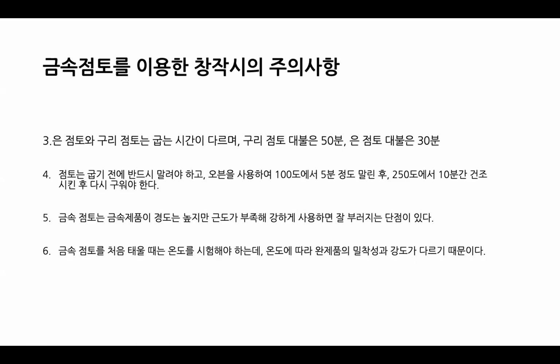The 5th point is the shortcomings of metal clay, which is also the continuous improvement of inventors. Although the hardness of work made of metal clay is up to standard, it lacks toughness and will easily break. This is very different from the cast silver products. The 6th one is that when the first attempt is made to mix metal clay, it's necessary to test the firing temperature first, so as to avoid the failure of production and waste of materials.